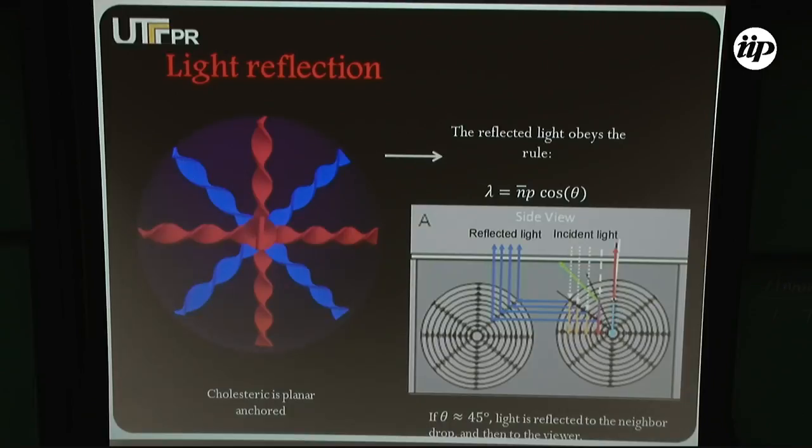And what happens usually is when you go to the middle of the droplet, it should reflect because of this criteria, so cosine theta, you should start seeing green light, right? But usually this light is just total internal reflected here, or the microscope doesn't collect it. But what is more interesting is when theta gets to 45 degrees. This is a basic reflection rule, geometrical optics, you get these incident lights reflect with the same angle, so it also reflects at 45 degrees, right? So what happens is light goes and finds another droplet, and then it's reflected back up, also at 45 degrees.